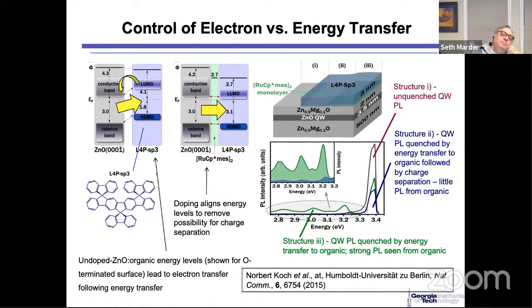And so that was all good, except that there was just a little bit of a problem of the alignment of the LUMO with the conduction band. The HOMO was right where they wanted it to be, but the LUMO was a little bit high relative to the bottom of the conduction band, such that when they ended up doing energy transfer to this L4P-sp3, they would get a back electron transfer to the conduction band to form, I guess, what you might call a charge transfer exciton, where the hole was here and the electron was there, and that was not emissive. So then what they did is they deposited something on the level of a nanometer of this dopant.